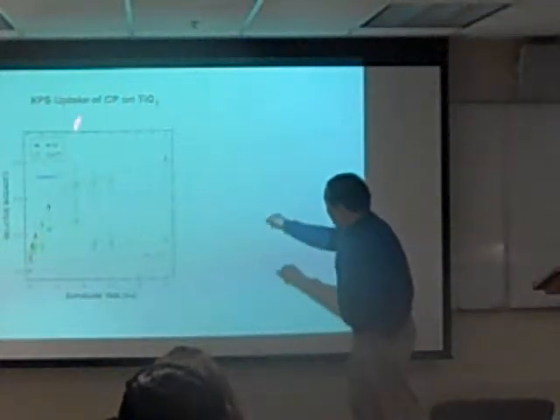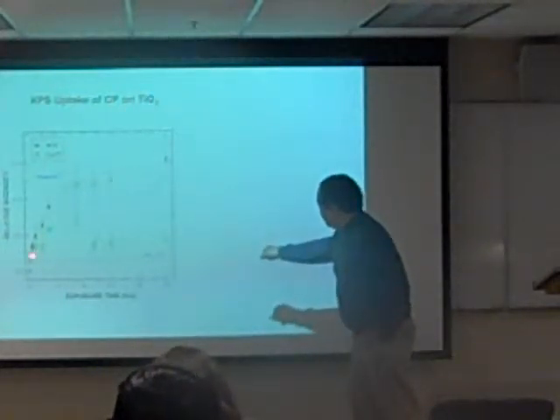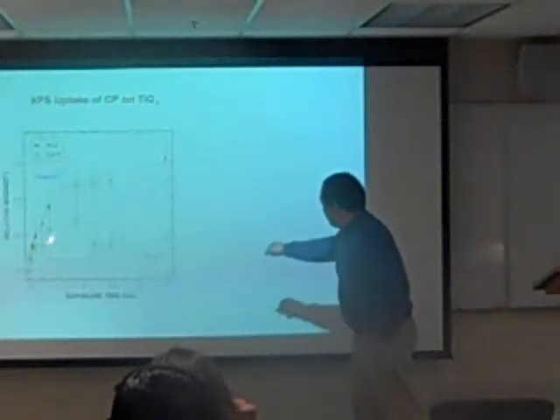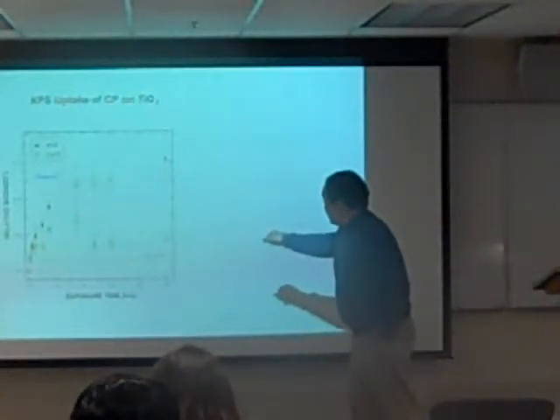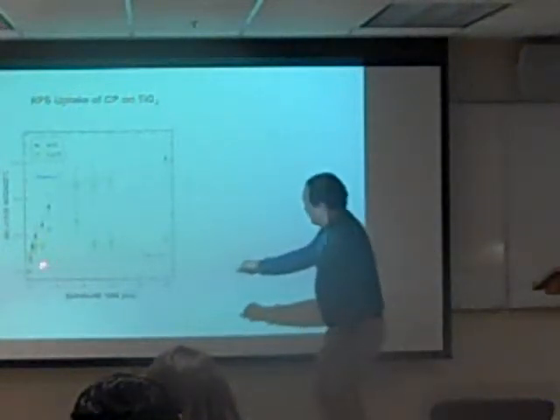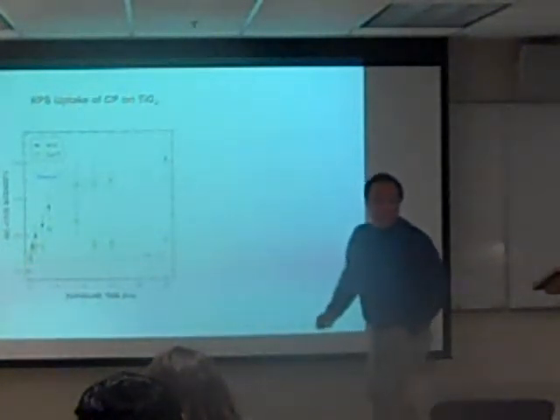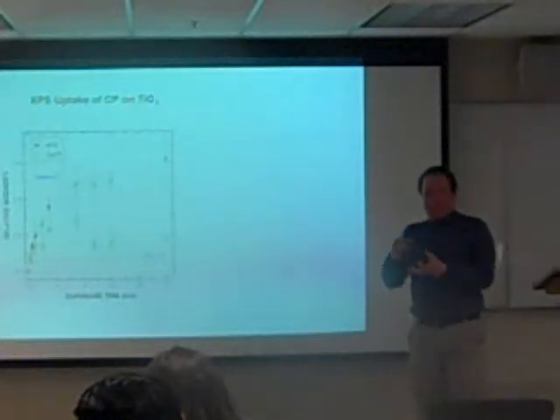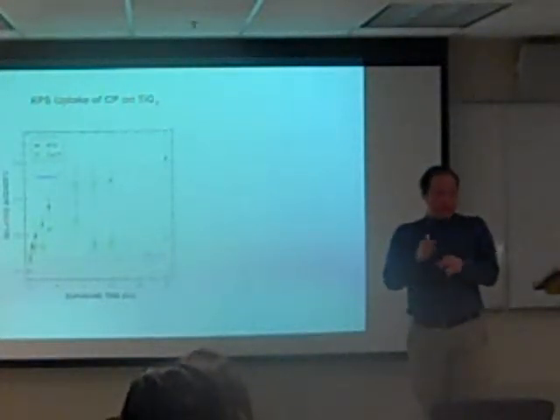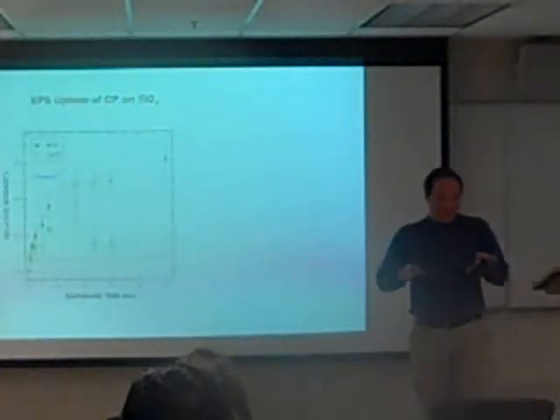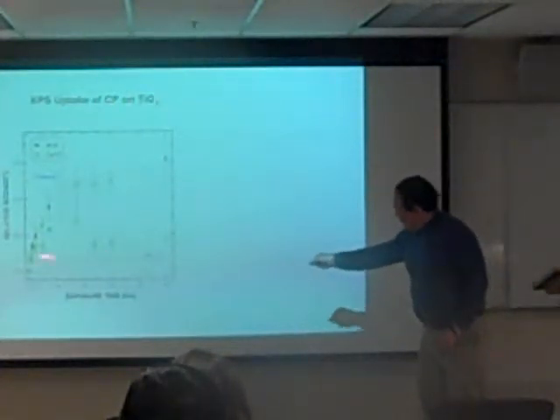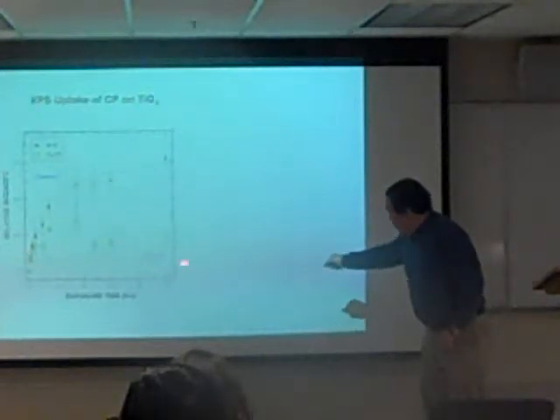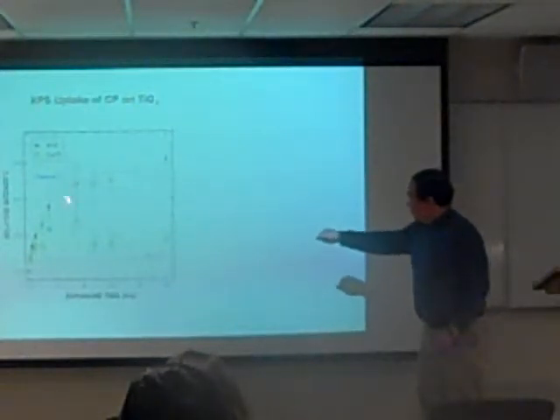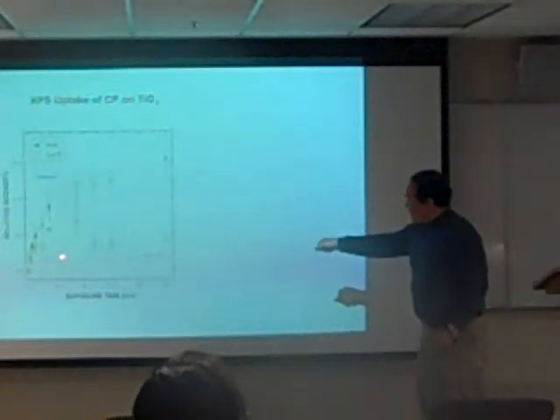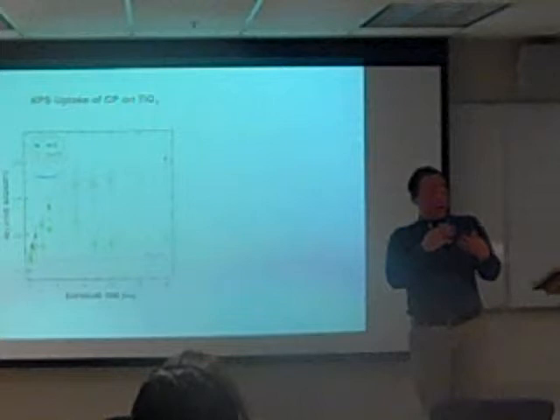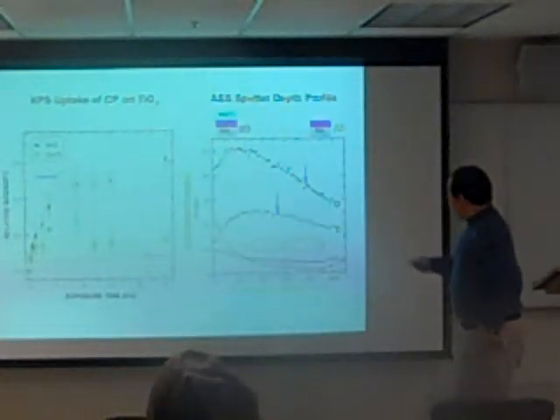This is an XPS uptake of calcium phosphate on the TiO2. So we can see phosphate grow here. You can see the calcium grow. And this corresponds to 1 monolayer equivalent. So basically, we just took the sample phosphate, assuming there's 10 to the 15th sites per square centimeter spin coated on the surface, and then did an XPS. That's what that horizontal line is. And this basically corresponds to that small amount of material where we think nucleation begins to occur. Now this is the sputter depth profile.